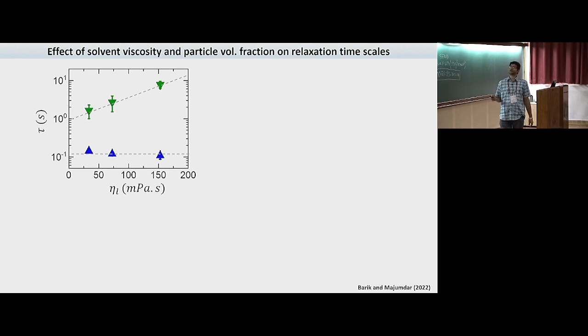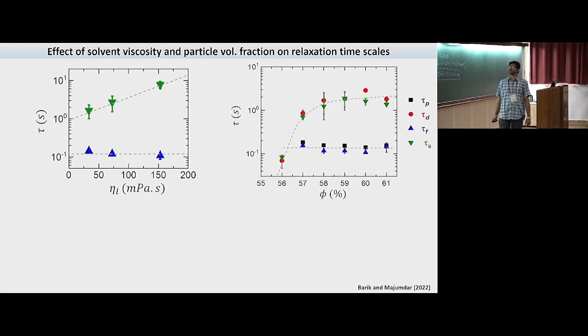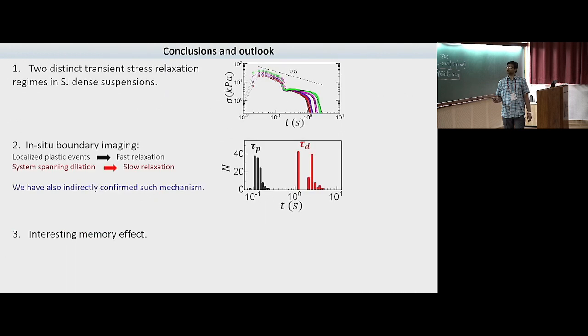And there is an interesting dependence. If we vary the solvent viscosity, you will see that the fast relaxation doesn't change, but slow relaxation changes. It becomes slower as you increase the solvent viscosity. So this fast relaxation time is sensitive to local environment, whereas slow relaxation is more sensitive to global variation basically. Okay, so I'll conclude that we showed that there are two distinct stress relaxation regimes in shear jammed dense suspension, and there is a nice correlation with this imaging experiment: plastic events give rise to fast relaxation, whereas dilation gives rise to slow relaxation, and we have confirmed such a mechanism.